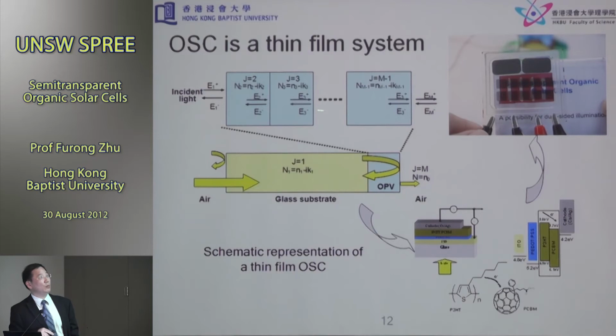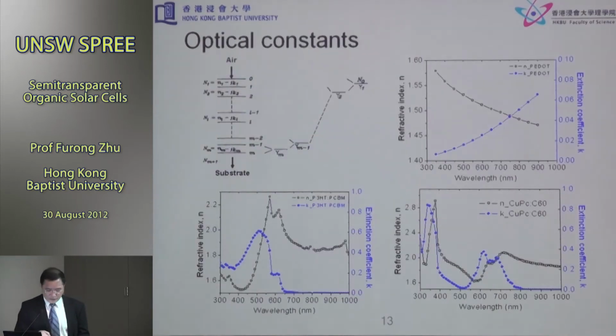And so, really, if you want to optimize the devices to have a high efficiency, one way to look at the system is that you want to understand how the light is distributed within this multi-layer system. You want to absorb most of the light in the area where it can generate excitons, for possible high efficiencies. So really, if you understand the distribution of the light in this thin film system, it will help you to design organic solar cells with high efficiencies.